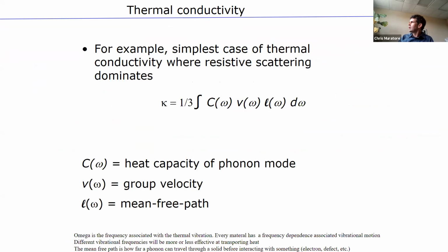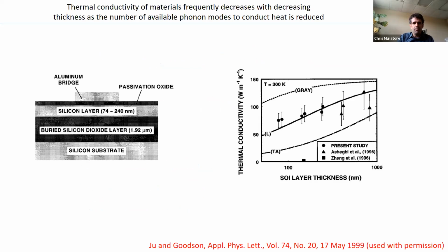I mentioned earlier that one of the big challenges with flexible electronics is thermal management. Just like the band gap varies with elastic modulus, thermal conductivity varies with elastic modulus too. For materials that aren't electrically conductive, the higher the elastic modulus, the higher the thermal conductivity. So if you're using polymers, which are super flexible with a low elastic modulus, thermal conductivity is also going to be really poor. And so what can we do to help with that?